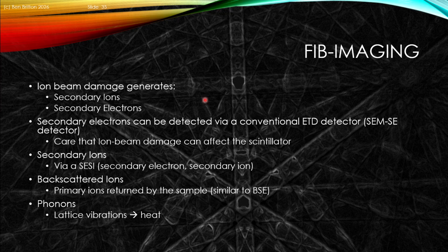So, what I've hopefully persuaded you so far is that we can use the FIB to image the surface of our sample, and effectively the ion beam damage and interaction will generate secondary ions and secondary electrons, and those two can be used to form a signal. The secondary electrons that are formed from the incident ions can be collected through a conventional ETD detector. This is the sort of SEM-SE detector. One small detail is that the incident ions can actually damage, if you're not careful, the ETD detector, and so you might have this as more of a consumable than in a conventional SEM.